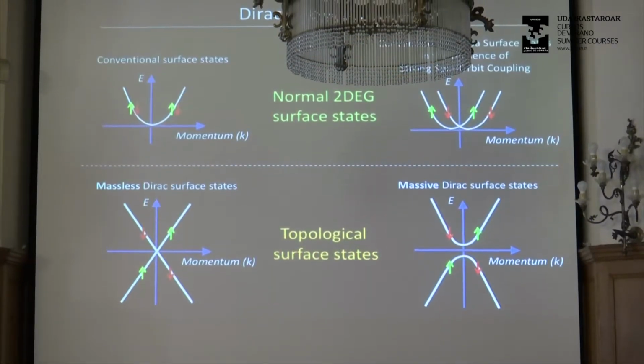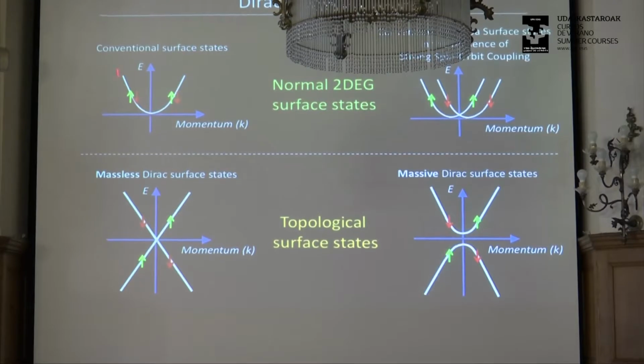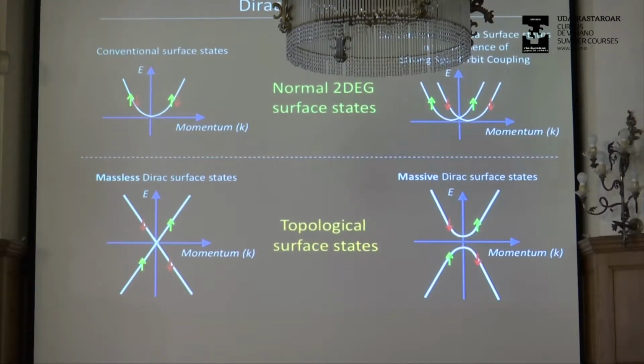So let me just tell you why these surface states are interesting. You can have the surface of a metal like copper. Copper 111 has surface states. Those surface states have parabolic dispersion. And at any given energy, you have two electrons, one with spin up and one with spin down, right? Just trivial surface states. Now, if you crank up spin-orbit coupling, like on the surface of gold, you'll get Rashba split surface states, right? But the problem here is, again, at any given energy, you still continue to have two electrons, spin up and spin down. And you can gap this out with magnetism or something like that, but the challenge remains that you have to move the Fermi energy into that gap and so on.